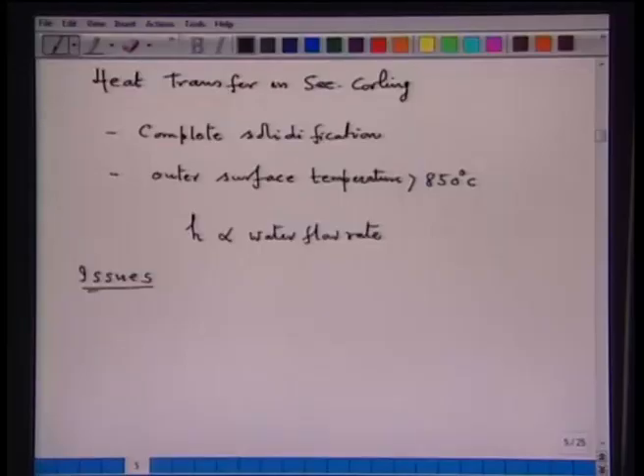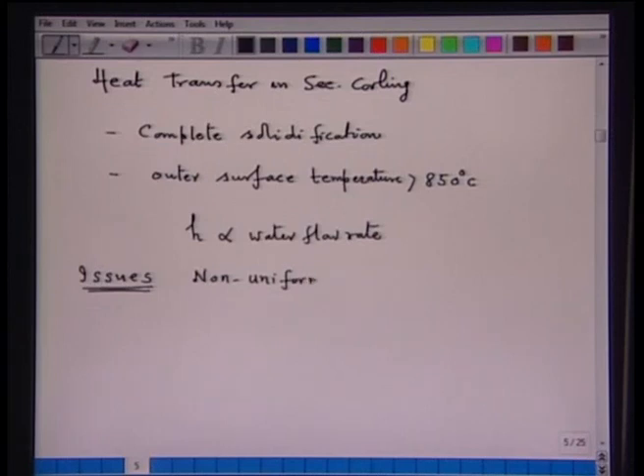Issues in secondary cooling — one issue is non-uniform cooling. Non-uniform cooling means the width is very large — for example, 2000 millimeters is the slab width and around 150 or 200 millimeters is the thickness. So placement of the water spray is important so that you have uniform cooling. Uniform cooling will not result in thermal stresses, but non-uniform cooling will result in thermal stresses on the surface and a tendency for surface cracking. This is about the heat transfer in the secondary cooling zone.